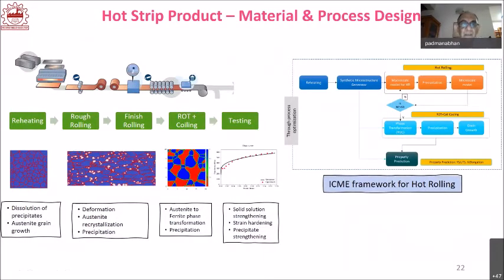This is a simple picture of hot strip HSLA. So that means reheating. Basically, what happens in reheating? So precipitate gets dissolved, austenite grains grow. In rolling, deformation is there. That means the grains get elongated, and austenite recrystallization is there. Of course, when you go to HSLA steel, austenite recrystallization may not be there if you have niobium and vanadium and titanium and so on. So that is where you see it helps you to develop into microstructures which are micron grain. So this is where the HSLA strength comes from.